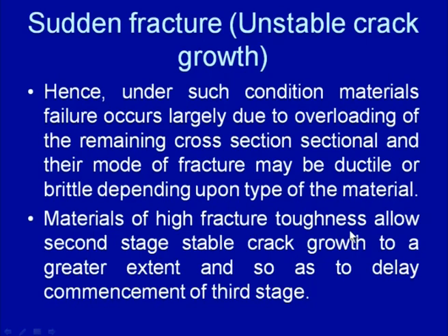So, materials of high fracture toughness allow the second stage stable crack growth to occur to a greater extent, so as to delay the commencement of the third stage. That means fracture tough materials will delay the completion of the second stage, which in turn will help in improving the fatigue life of the component.